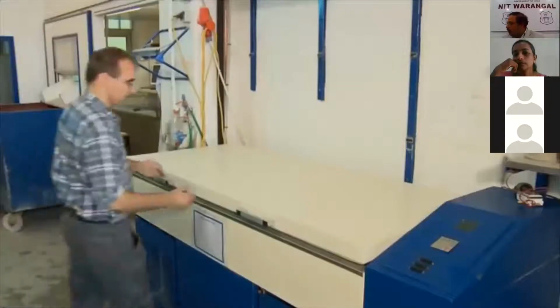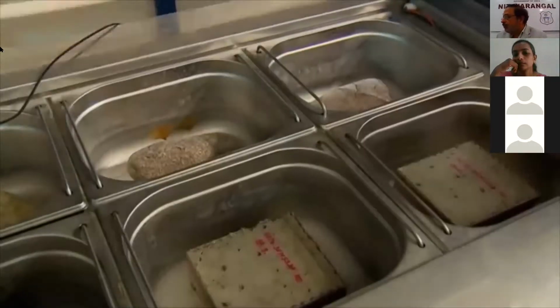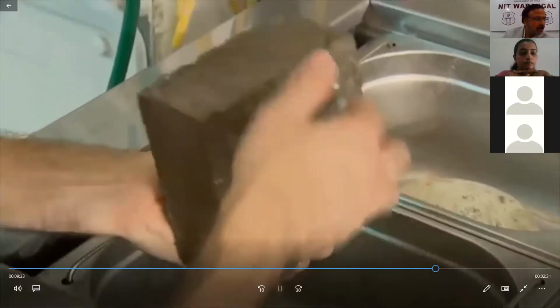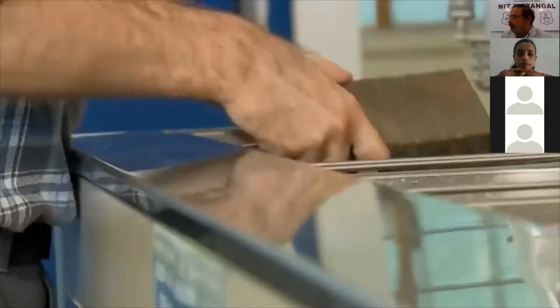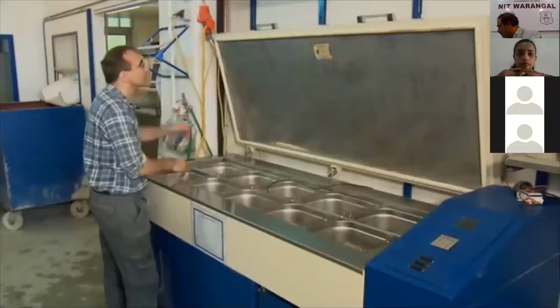Engineers are carrying out additional tests with recycled concrete samples in the lab's cold chamber. These tests indicate that recycled concrete is far more resistant to frost and de-icing salts than previously thought by lawmakers. The state of Rheinland-Pfalz has a research project aimed at changing current regulations to substantially increase the amount of recycled aggregates used in concrete. It's also aimed at processing all the materials found in construction waste in order to reuse them in further construction. That would create a closed cycle of materials within the construction industry.